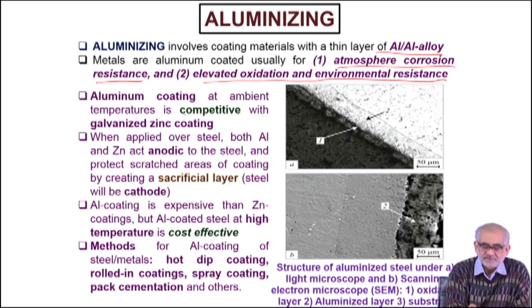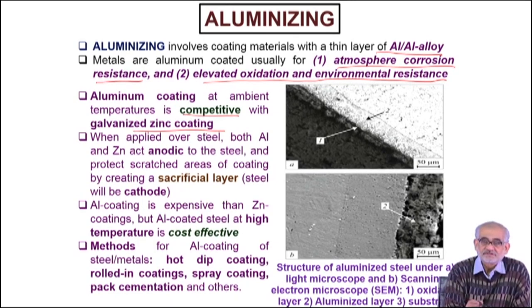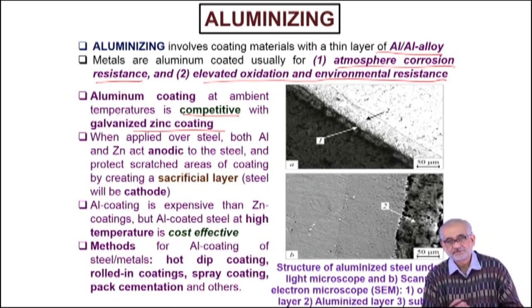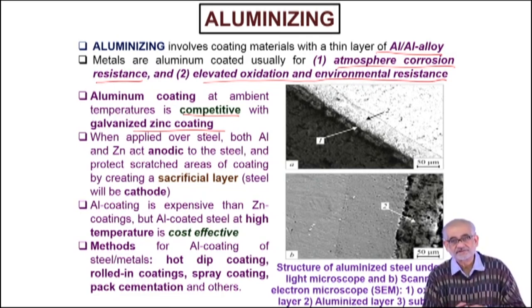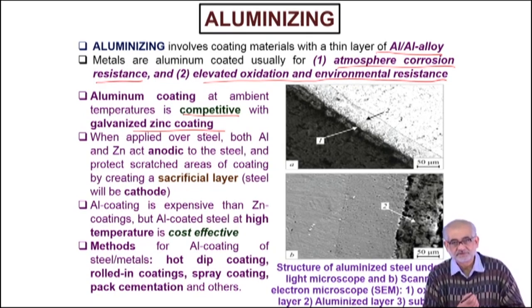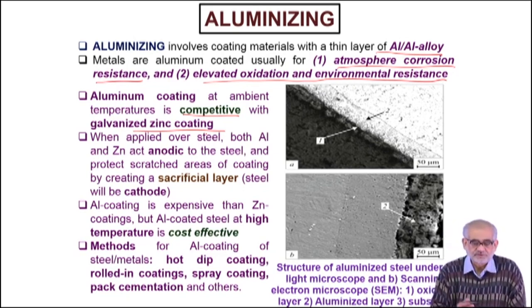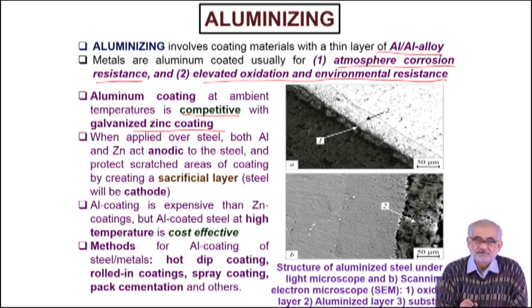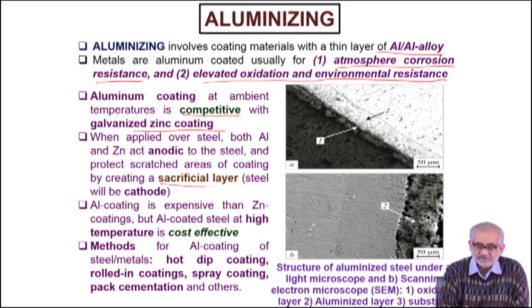This process is very competitive and comparable with so-called zinc coating on steel, but remember zinc coating is never exposed to high temperature. Whenever you expect steel or metallic substrates to be exposed to high temperature — like compressor blades made of titanium or turbine blades made of single crystal nickel alloys exposed to around 1050°C — at such high temperatures we require something different than zinc, and aluminium is one of the biggest candidates for that condition.